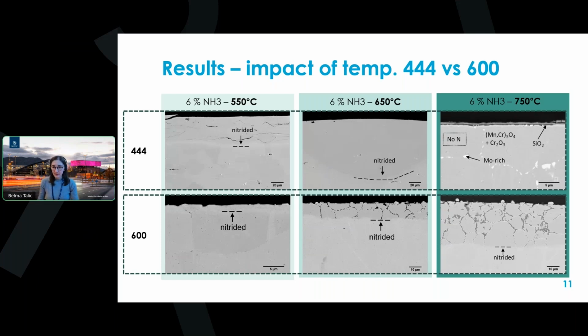The differences in the temperature dependence of the different alloys can, to a large degree, be understood if we inspect the sample cross-sections in SEM. Here we see alloys, the ferritic stainless steel 444 and the nickel-based alloy 600, shown at 6% ammonia, 550, 650, and 750 degrees centigrade.